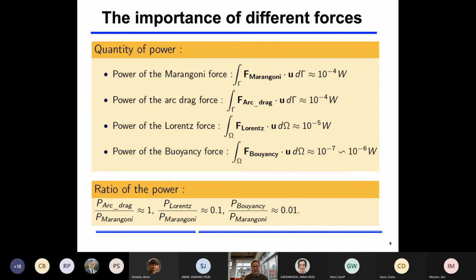So now look into the importance of these different forces. Generally speaking, we do not have accurate data. We try to measure it, it has been very difficult. Those are probably the rule of thumb to look into. So we probably look first at Marangoni force, probably 10 minus 4-ish, and then similar level to arc drag force. And Lorentz force is one magnitude lower. Buoyant force is even lower, depending on, anyway, this will depend on materials.